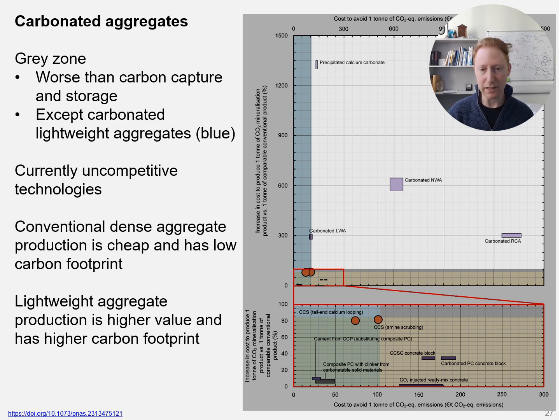The problem here is that conventional aggregate production is cheap and it also has a low carbon footprint. So it is more expensive to carbonate a material rather than just to produce aggregate. There is also not much CO2 avoided by avoiding conventional aggregate production because its carbon footprint is pretty low. On the other hand, lightweight aggregate, expanded clay production, is higher value and has a higher carbon footprint, and that's why the results for this product are different.